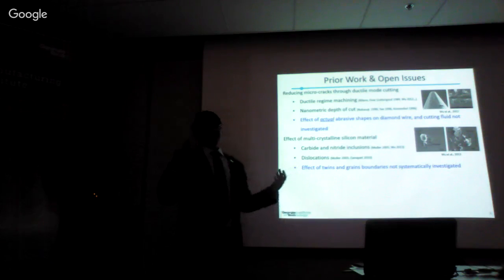Moreover, some work had been done on the dislocation at the grain boundaries and at other parts of multi-crystalline silicon. And we know from prior literature that dislocations affect the ductile flow of material and how they could affect the cutting of multi-crystalline silicon. However, there is no systematic work done on the effect of grains and twin boundaries in multi-crystalline silicon when scribing or cutting by diamond wire sawing. So in my PhD thesis, I look into this aspect of cutting multi-crystalline silicon by doing scribing experiments across grains and twin boundaries systematically. Moving on to the next challenge, which is the wear of diamond.